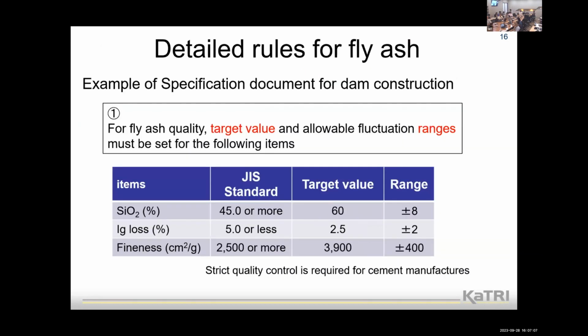And then, in addition, at most construction sites, in addition to the JIS standard, detailed rules for fly ash are decided. For example, this slide shows my experience at the dam site. For example, in the specification document for dam construction, for fly ash quality, target values and allowable fluctuation ranges must be set for the following items, such as SiO2, ignition loss, and fineness.